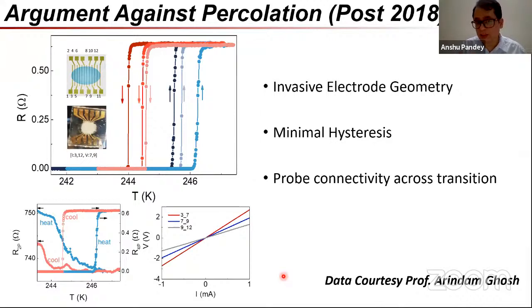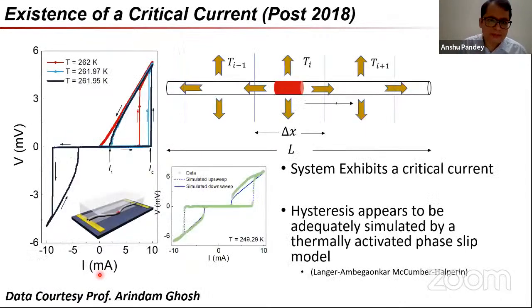They were able to show many things which we at that time hadn't. For example, they were able to show that when we pass through a transition, the two probes still remain connected. In our case, we had simply checked the two probe connectivity at the lowest temperature, meaning at the zero resistance state, but not really tracked it through the transition. This is something totally new. So probes are connected through the transition.